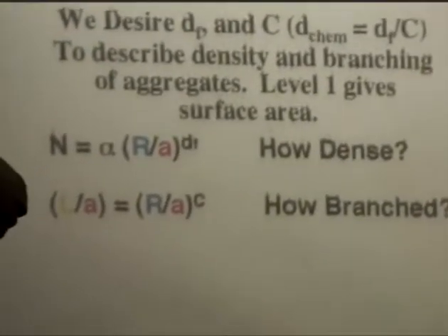Typically you plot the data as log intensity versus log scattering angle, and this is a typical shape you'd see from this kind of material. These materials, including the pyrolytic, the solution route, and these aerosol gel materials, form aggregates where the primary particles would be on the order of 10 to 50 nanometers, and the total aggregate can be up to about 0.1 micron.